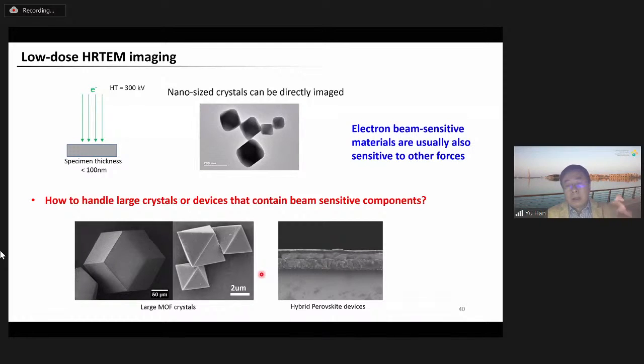Well, so in the previous slides, most of the examples I showed you were MOF images collected from nano-sized MOF crystals without specimen preparation. Okay? However, in many cases, the sensitive materials we wish to analyze are in the form of bulk crystals rather than nanocrystals, right? So now the high-resolution imaging of sensitive materials has become possible with the new techniques developed. So now is the time to think about TEM specimen preparation so that we can extend the application of this new imaging technique to large crystals, say micron size or even millimeter sized crystals.